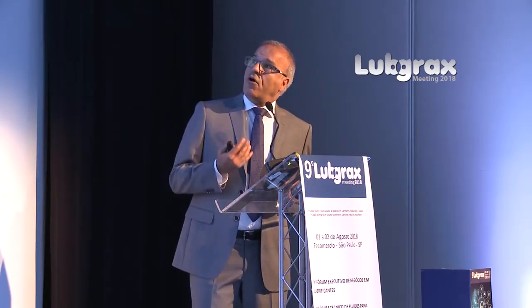So in summary, I went through what we have done. The strength of using high viscous naphthenic oils, both the reference oil as well as T600, was demonstrated for three different types of greases. These strengths are at least part of the solution to the situation of the lithium grease and lithium market that we are facing, and this challenge is going to be combined with the rationalization of the base oil industry, which is another story.